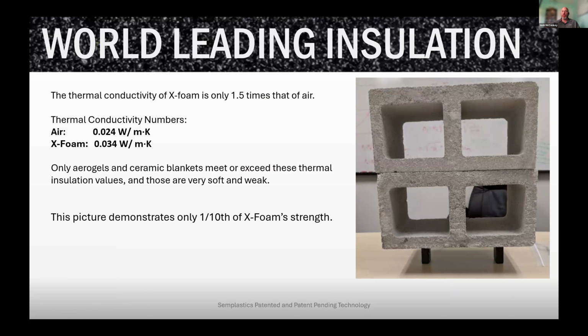But what I have here is that this stiff but not brittle ceramic is able to hold a lot of weight. What we show here with these concrete blocks being held up by two 2 by 1 inch pieces is only 1/10 of the compressive strength. I could actually then go stand on those concrete blocks and the ceramic foam would not crush.